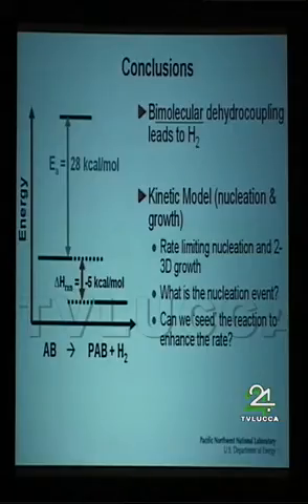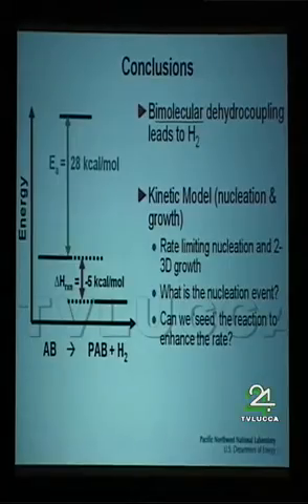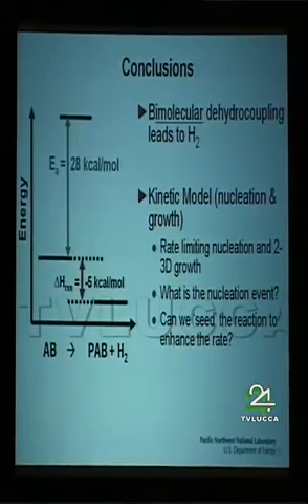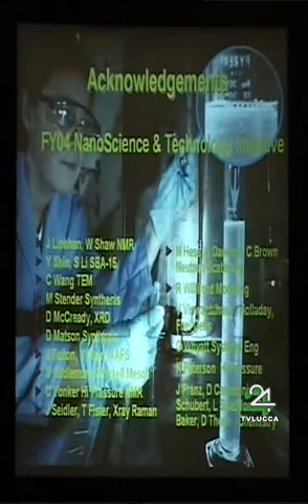So, a bimolecular reaction, not a unimolecular reaction. Kinetic growth, nucleation, and it's somewhere between 2 and 3D growth. And so the critical question really is, what is this nucleation event? Because if you have that, you can possibly enhance the kinetics. And so we can seed the reaction and get the hydrogen off at lower temperatures, or faster rates at the same temperature. And so that sort of wraps it up.